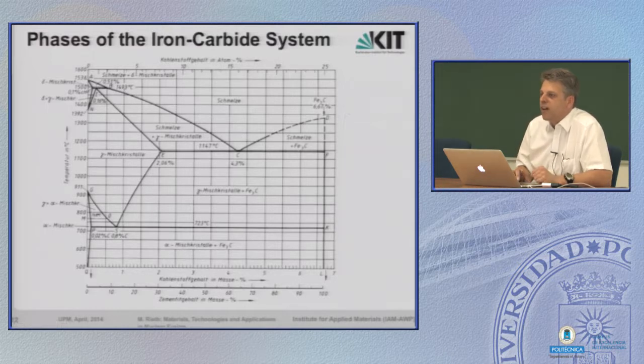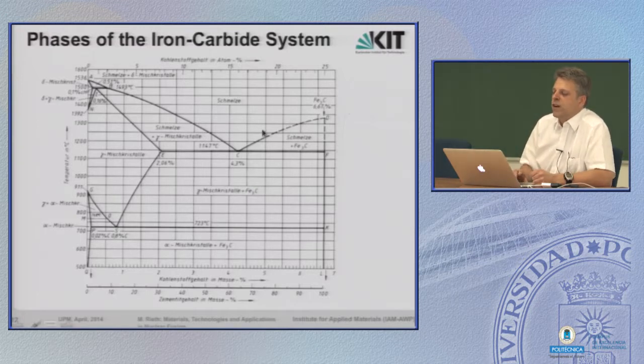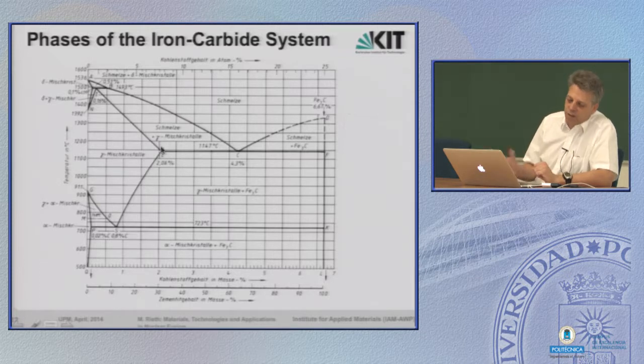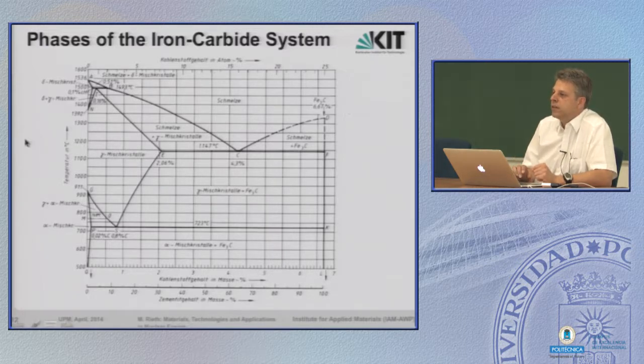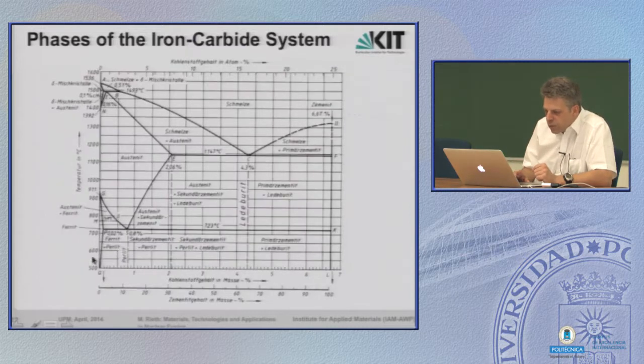This is what we call cast iron. That's a very brittle material and, yeah, not very useful on that point. That's why we skip from here, from carbon contents more than 2%, skip this completely. The interesting point where we later will focus on, austenitic steels, they have almost no carbon inside, and also the 9% chromium steels like Eurofer for fusion application have a carbon content of 0.02%. So we are really here on the very left hand side.